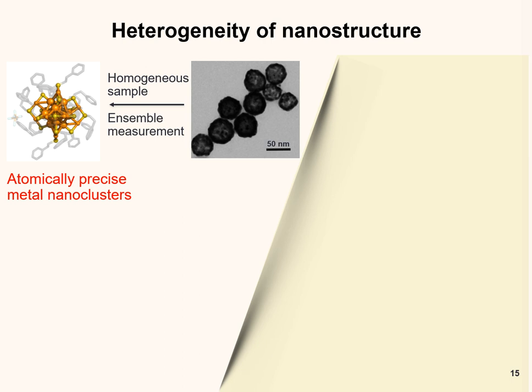Previously, I talked about how they have so many applications, you can use it for that device. But for physical chemists, we love its atomic positions. Remember, this is a purely gold nanocluster. Between cluster to cluster, they are identical. They have the same number of gold atoms. They have the same number of ligands. The structure is the same. When we are measuring their property, we can easily correlate structure with property easily and accurately.